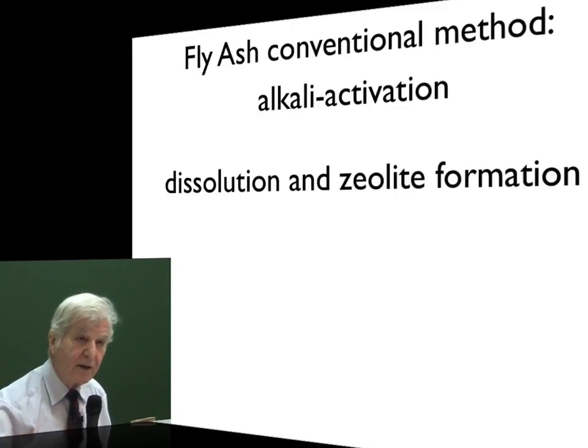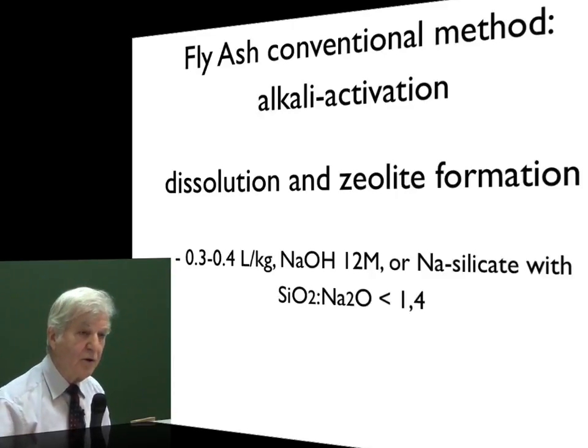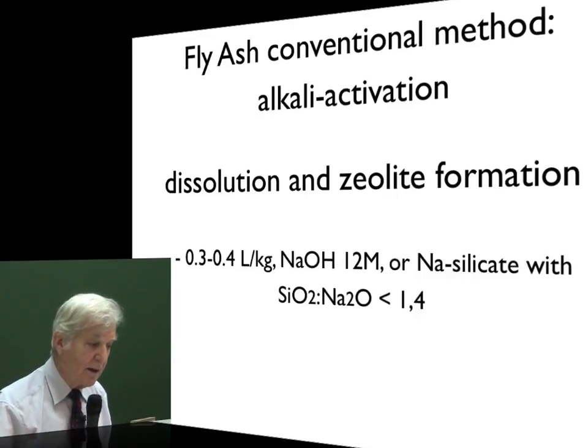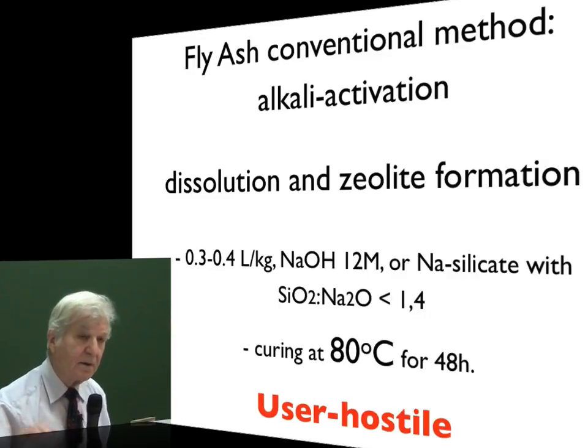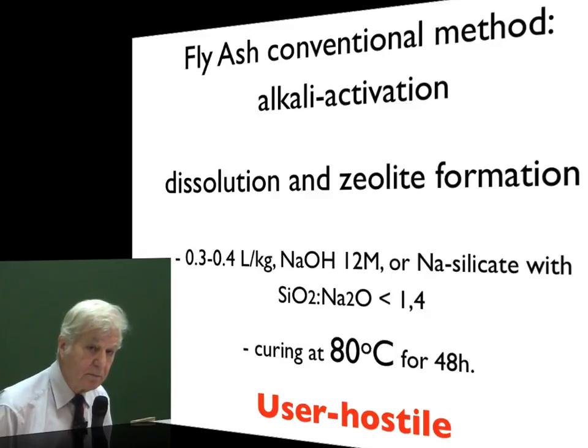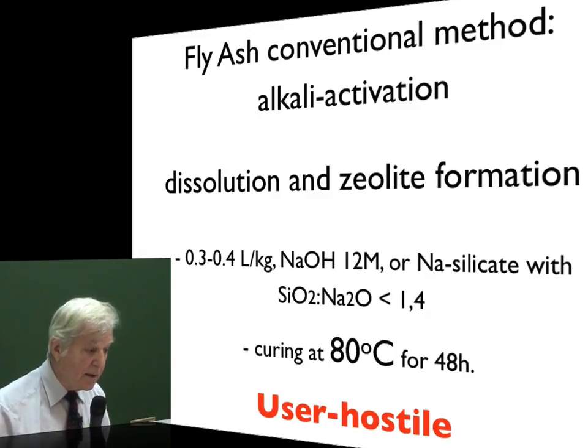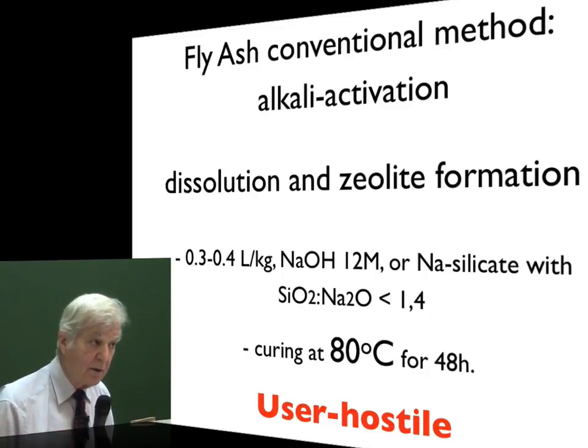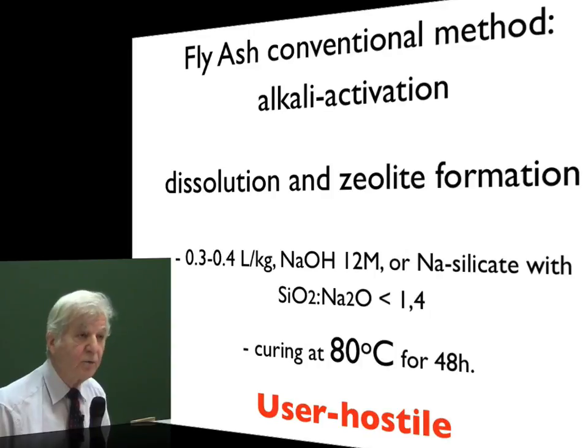We dissolve the fly ash, zeolite formation. We use a lot of NaOH and Na-silicate that are caustics. We cure at 80 degrees C, and this is user hostile. These guys never put their finger in the slurry. But this is what they are doing. 80% of the papers written on fly ash are made with this system. And this is what they are comparing. It is obvious that to produce this high amount of NaOH and silicate, you need a lot of energy and you emit a lot of CO2. But this is not what we are doing.